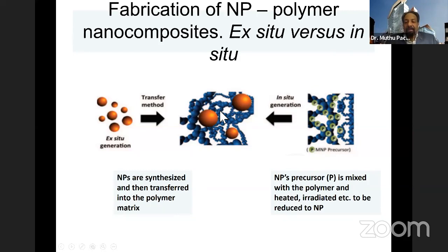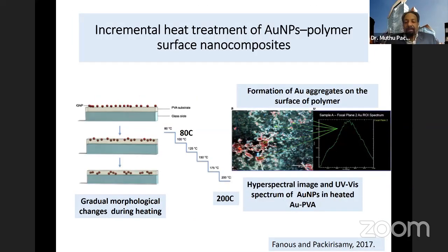So we get composite from ex situ and in situ types of approaches. Another interesting thing is that we can thermally drive these nanoparticles into different depths of the substrate. So temperature and time could be good parameters to control the size as well as the distributions of these nanoparticles in the polymer nanocomposite.